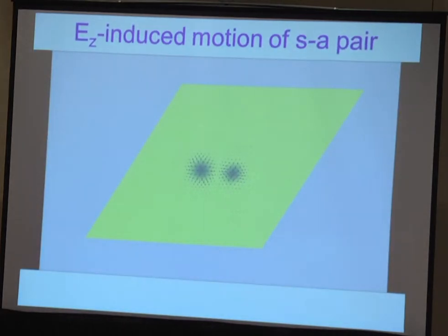So we can now actually perform a kind of inverse effect. Now I apply that component of electric polarization, and this is a Skyrmion, this is a Skyrmion. And what happens is that the Skyrmion rotates suddenly by angle pi, and the anti-Skyrmion rotates by pi over 2. Maybe I can go back once again. In this way, the relative angle between spins along the line connecting the Skyrmion and anti-Skyrmion remains the same.